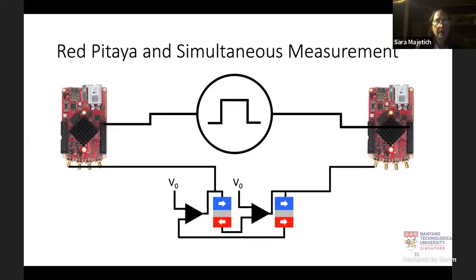In hardware, the way it works is we have circuit boards that are triggered together and are able to capture very fast response. And they are connected to 2 coupled magnetic tunnel junctions. And we can control the state of the magnetic tunnel junctions using voltage programming. Right now, I'm showing them having the same voltage, but they could be different voltages. And that's giving an additional bias. But what we see, looking at one going into the other, the output from the first tunnel junction, if that is a high resistance or a low current, then it's going to reduce the overall voltage in the next one. That's going to shift in such a way so that it is favoring.